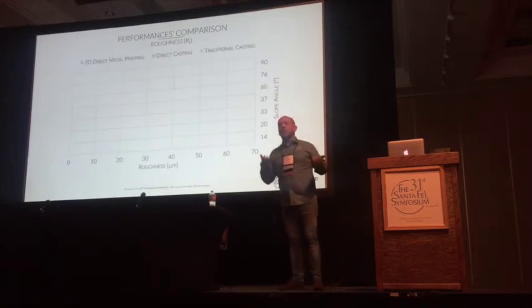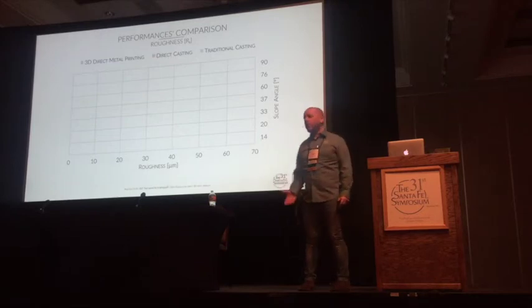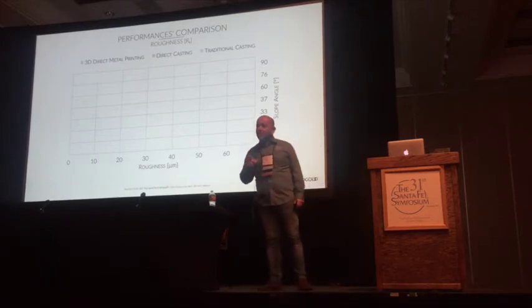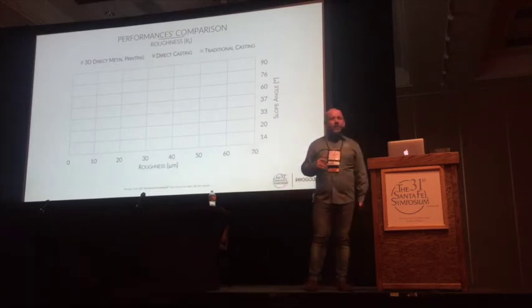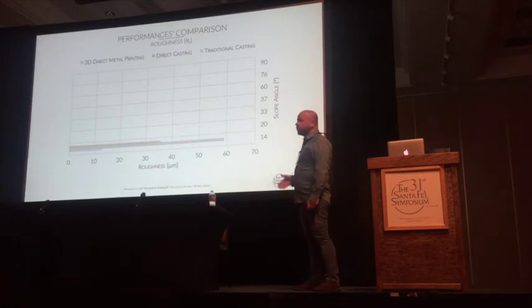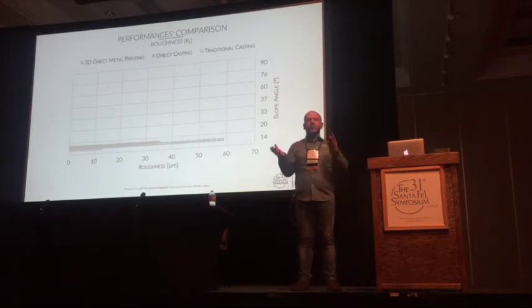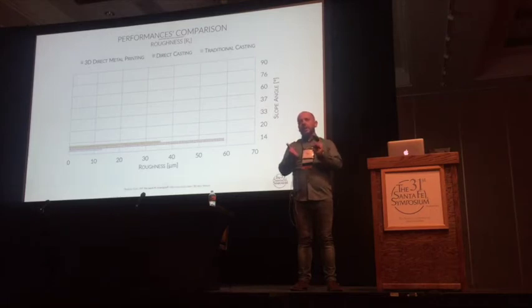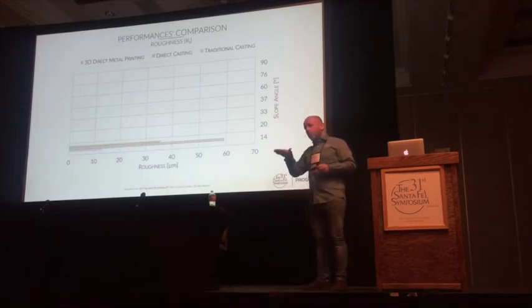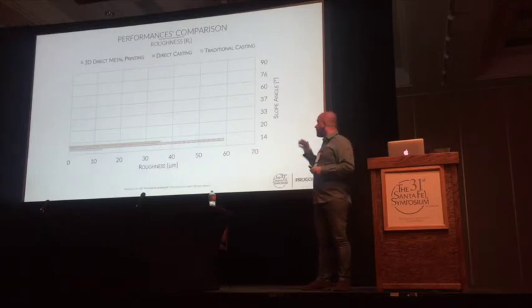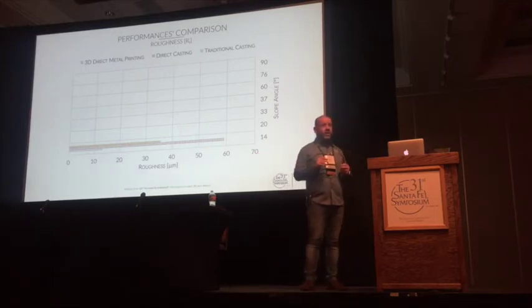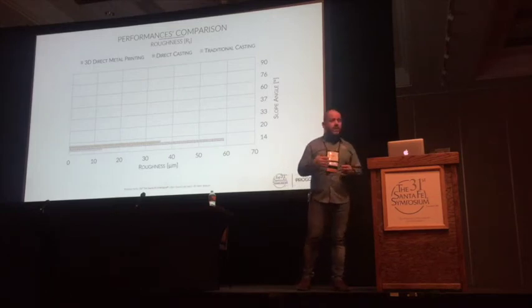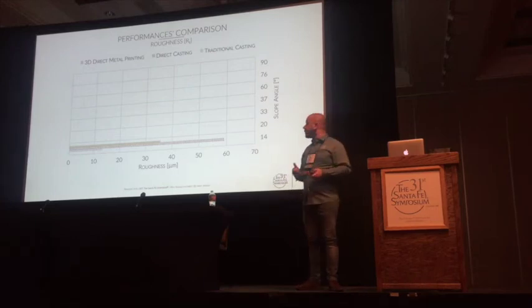Let's go to the roughness. This is one of the weak parts of 3D metal printing, but we will see that direct casting is not much better. On the y-axis we have the slope angle. If some of you remember, we were printing parts with different slope angles, because 3D metal printing has different roughness according to the slope angle on the building platform. When the part is almost horizontal, the roughness of 3D metal printing is very, very high, something like 4 times higher than traditional casting and 1.5 times higher than direct casting. But when we go up with the angle, things get better and better.